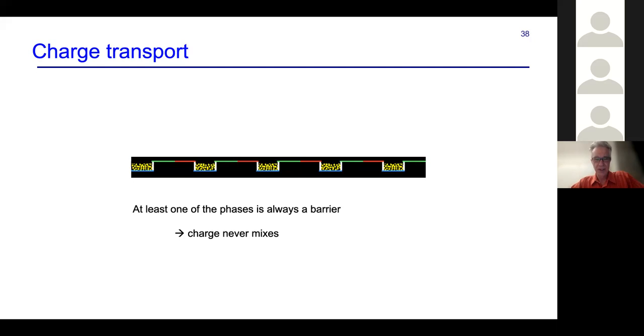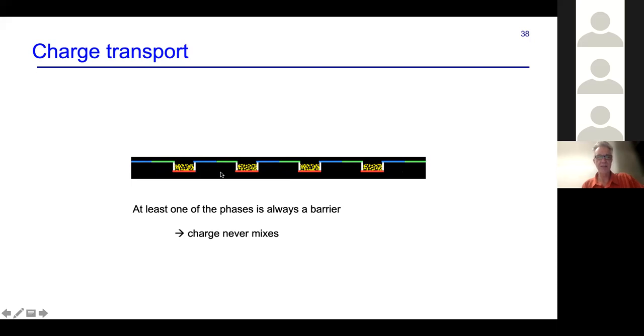If you look at this mesmerizing little video for a while, you'll realize always one of the electrodes is high and it's acting as a barrier that stops the charge from mixing from pixel to pixel. But in the process of, how do I make this go again? Let me see if I can do this again. There we go. In the process of sequencing through these voltages, high and low, you can see that you either have one in the low condition or two in the low condition, which hold the charge, and so the charge moves along sideways.